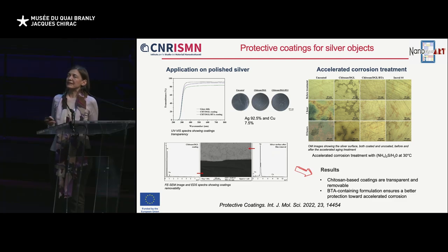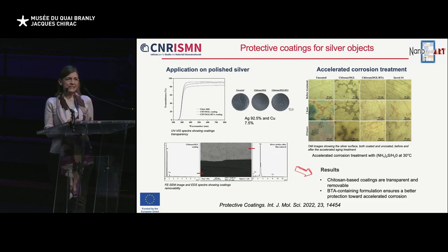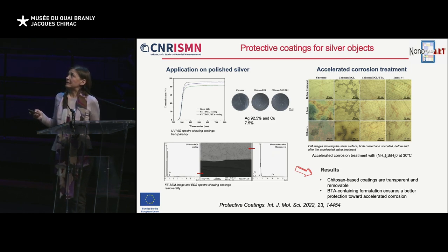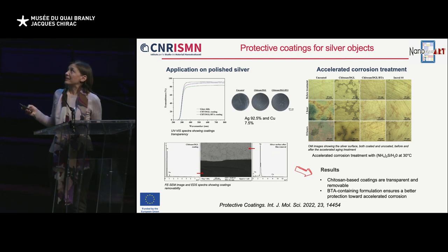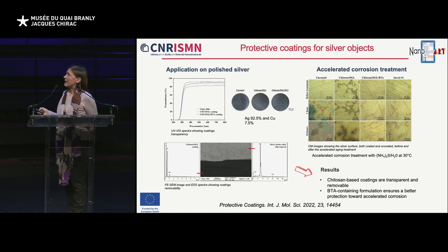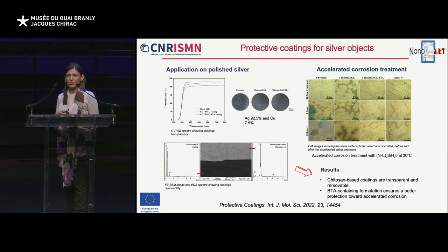So in addition, these formulations were also used to protect silver mock-ups. In particular, we used the sterling silver, which is one of the most common alloys used in particular in metal artifacts. And if we look also in this case to the results of accelerated corrosion treatment in the presence of ammonium sulfide, in this slide we can see the optical micrographs. We observed that the uncoated disc is quickly degraded, and the best performing are the commercial products and the chitosan formulation containing benzotriazole. These coatings are quite transparent and completely removable because by using a scanning electron microscopy and by removing the biopolymer coating using a cotton swab embedded with water and ethanol, we cannot appreciate the presence of any residues, and this was confirmed also by infrared spectroscopy.